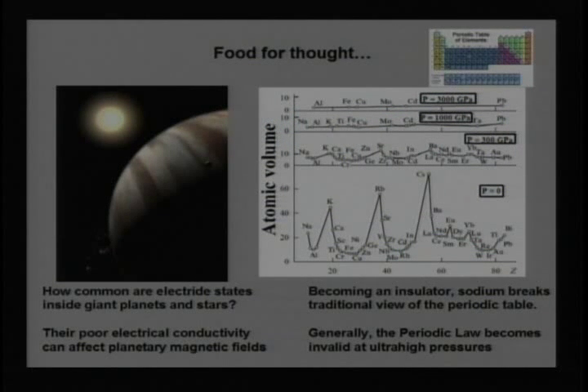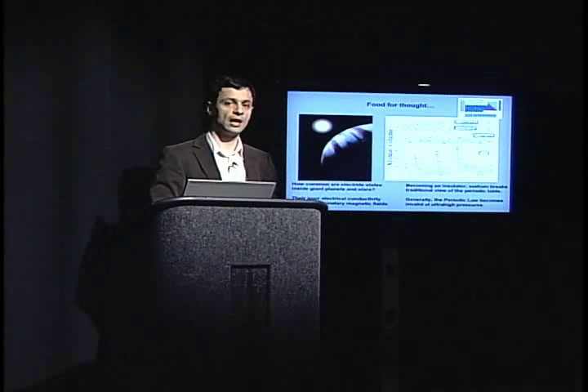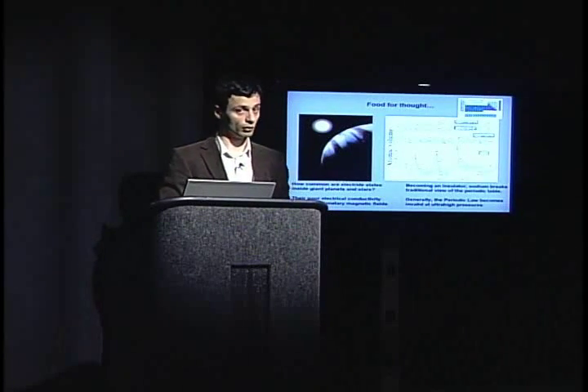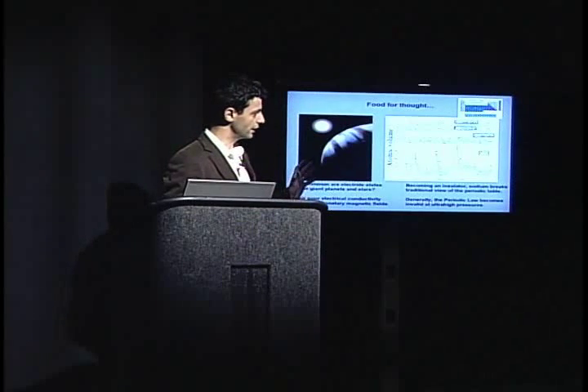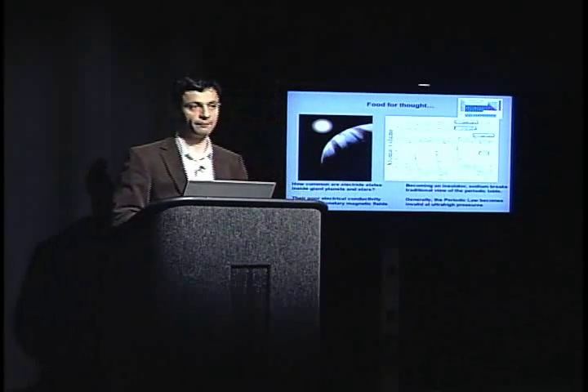And in fact, at pressures like 10 million atmospheres and more, many elements are now described by the free electron gas model. And rules of chemistry will no longer apply here. So we can see that under pressure, indeed, the periodic law becomes invalid. And one of the manifestations of this is the fact that sodium, an alkali metal, becomes transparent at high pressure, at experimentally reached pressure. We predicted a crazy phenomenon using theoretical simulations. Experiment confirmed it only afterwards. I think it shows the predictive power of modern theory.